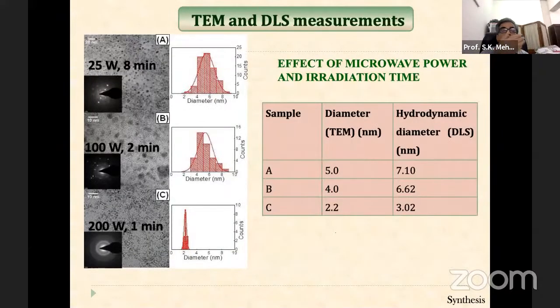In this, you can see if you are using 25 watt for 8 minutes, or 100 watt for 2 minutes, or 200 watt for 1 minute. If you use 200 watt for 1 minute, you can get very nice, small particles. But if you are using 25 watt, then you require more time, that is 8 minutes, and the particle size is also slightly bigger as compared to 200 watt for 1 minute.